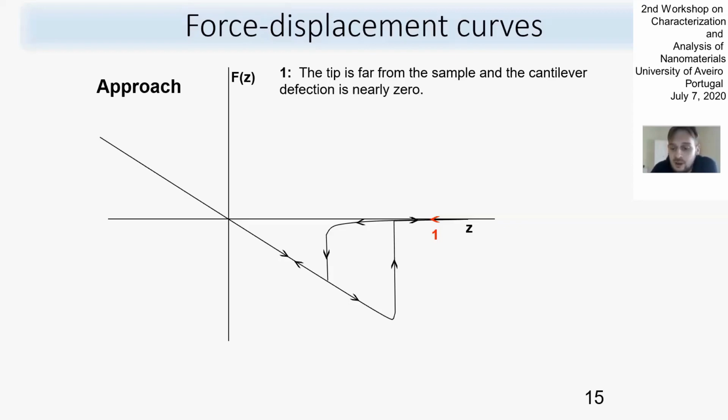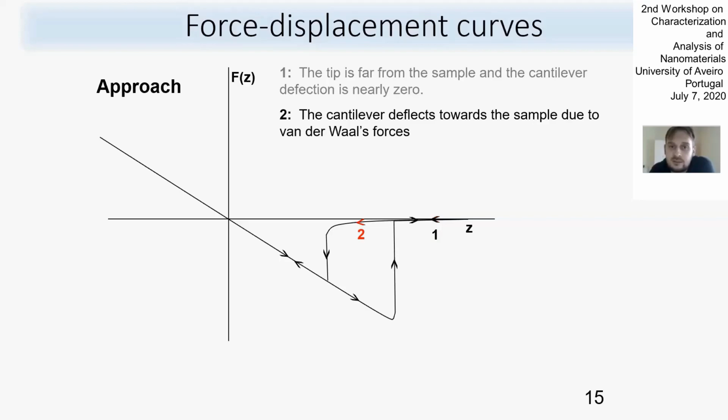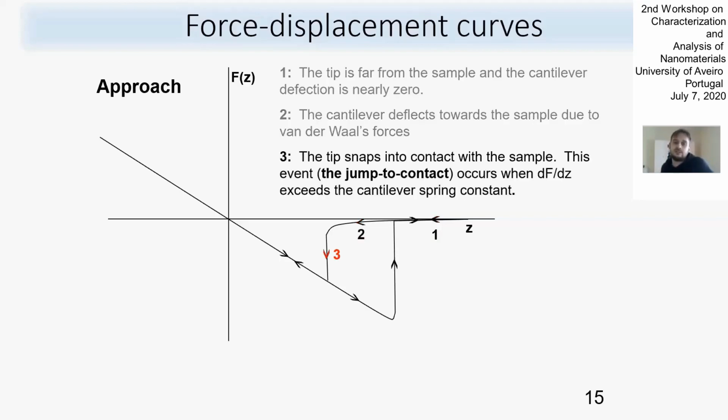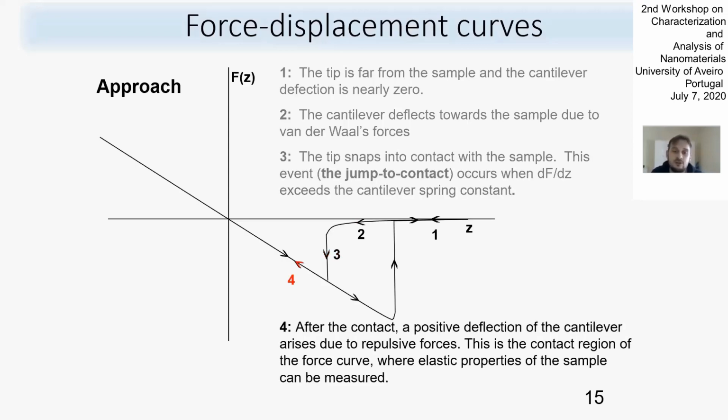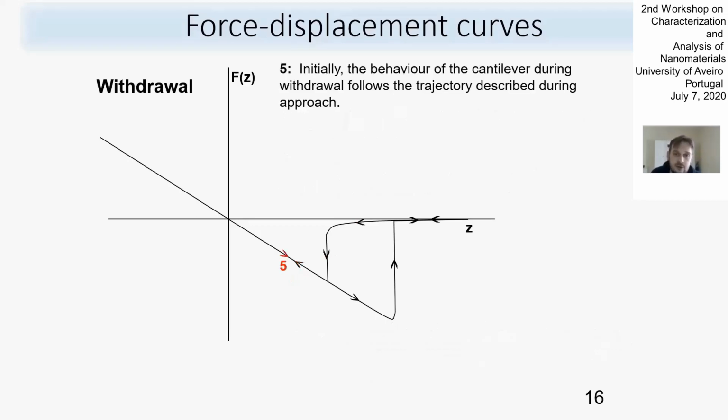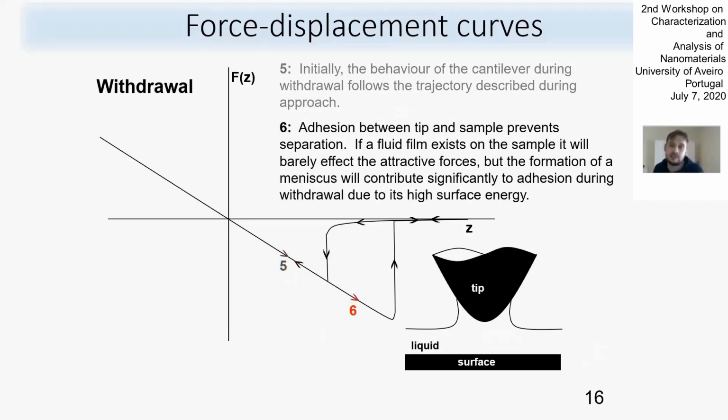And actually this makes sense. But the question is, what kind of hysteresis is what we observed in that curve? This hysteresis usually happens because of the specifics of the interaction between tip and surface. If we don't have any other forces except van der Waals, we will see only the linear dependence without any hysteresis. But if we have some other forces, like adhesion, for example, we always have a liquid